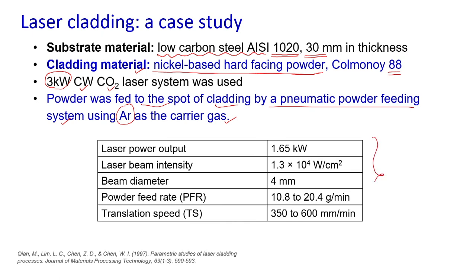These are the process parameters on your screen that were applied. The laser power was about 1.65 kilowatt, beam intensity was about 1.3 × 10^4 watt per centimeter square, and beam diameter was about 4 mm. PFR, that is the powder feed rate, was about 10.8 to 20.4 gram per minute. These are the two important parameters here: PFR, powder feed rate, and translation speed, the speed of movement of the substrate, which is about 350 to 600 mm per minute. So, scan speed and powder feed rate, these two are the important parameters to be considered during this case study.